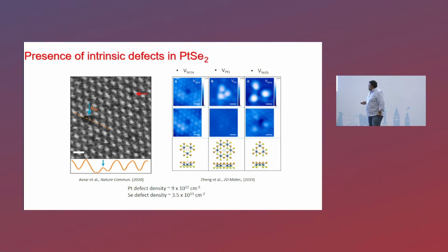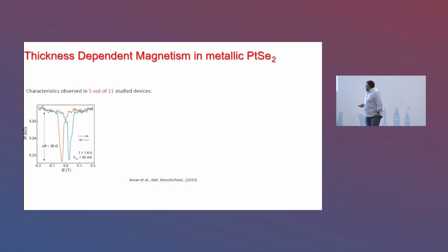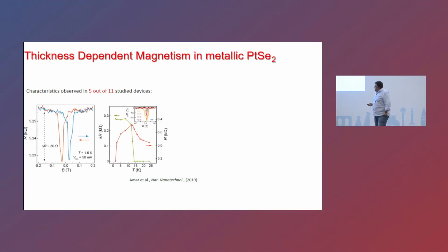And these results were also confirmed by another independent study with some STM analysis, showing that the material is full of defects. We made lots of devices, and although the material is supposed to be non-magnetic in the pristine form, we could see very hysteretic magnetoresistance in nearly half of the devices that we studied, with a Curie temperature around 13 Kelvin.